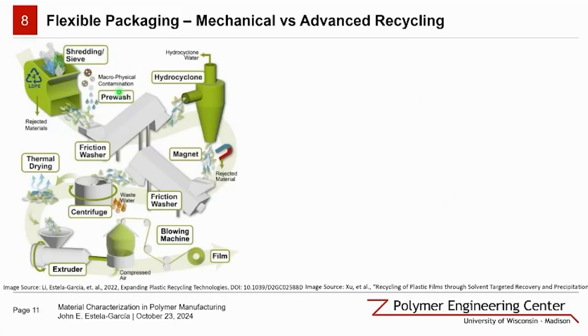It starts with the recovery and sorting that occurs at a material recovery facility. There's the shredding steps and washing steps and drying steps that are required in order to clean the material as much as possible to prevent any contamination, or at least most of the contamination. Right, once you have the material dried, it is then fed to an extruder where it can be pelletized before being recast into a film. While this method is well established and used, it does face limitations in handling contaminated or mixed plastics, and this often results in degraded properties.